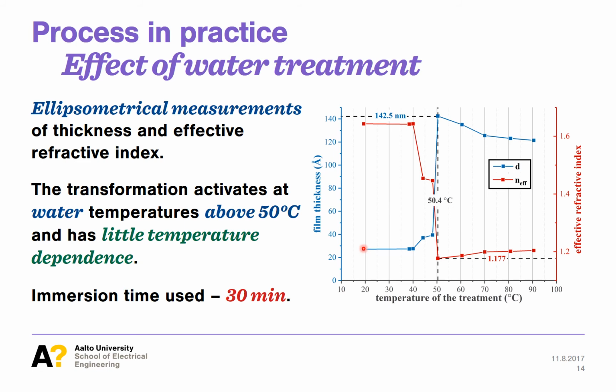We not only have a gradient refractive index, but also the effective or average refractive index of our film is around 1.2, which is very close to index match value for glass, which is 1.22. In addition, ellipsometry has helped us to choose the film thickness for accurate positioning of the transmittance peak at a desired wavelength. Thus, even though ellipsometry does not measure the real thickness and refractive index for grass-like alumina, it is still a useful measurement technique as the effective values provide quality control.